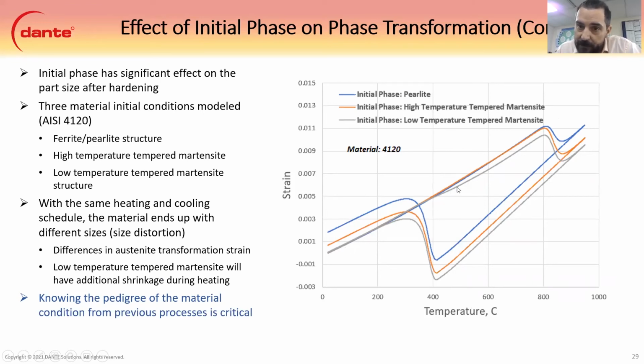You can see the orange line coming through here, and there is a little bit of a dip here at the higher temperatures, past the tempering temperature, and then the austenite start is a little bit different. And then the gray line is actually low temperature martensite, so it happens at a temperature of maybe 250 or something around here. And then you can see the effect on the coefficient is no longer a straight line anymore.